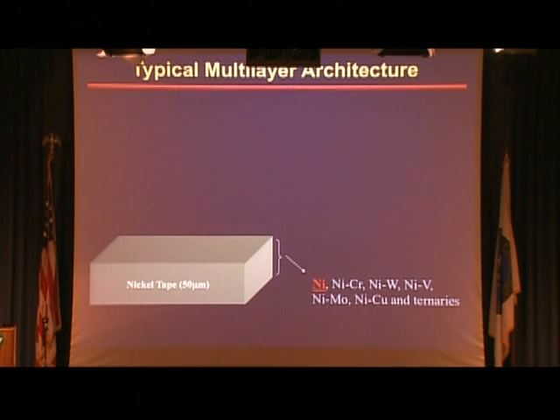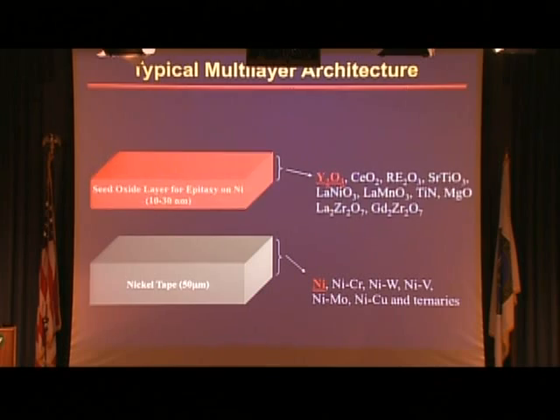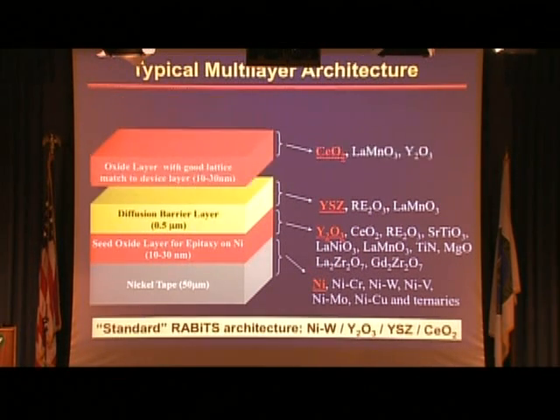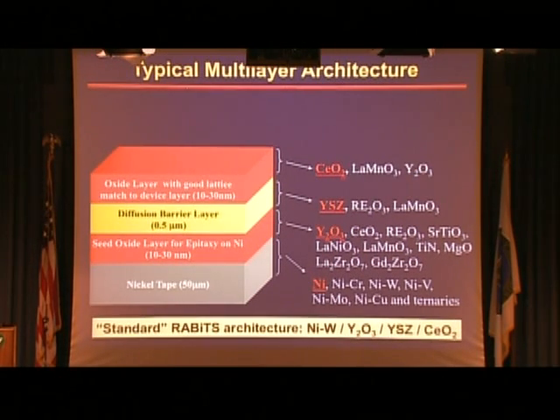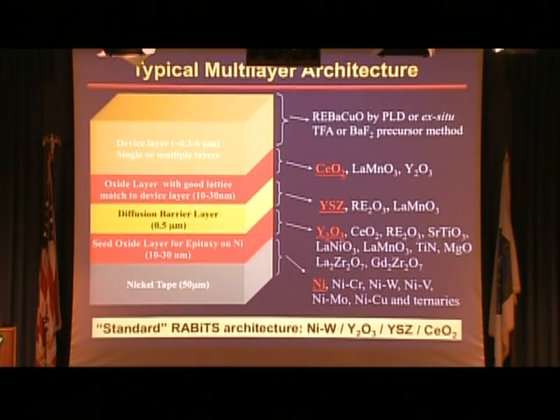So what we're doing in this process is we start with the metal tape, which is single crystal-like, and we can choose the composition of it to match the physical property of interest for the application. We deposit the first layer to get the right atomic orientation with this metal tape. We deposit this diffusion barrier layer to prevent atoms from here going up to your device layer. And then we deposit this third layer here to get a good match with the device layer, which in this case is the superconductor. And the basic stack is we have this metal substrate. We have 3 oxide buffer layers, yttrium oxide, YSZ, and cerium oxide.